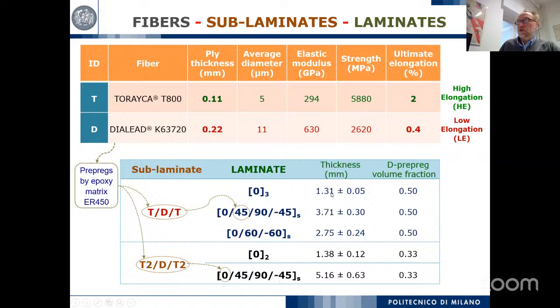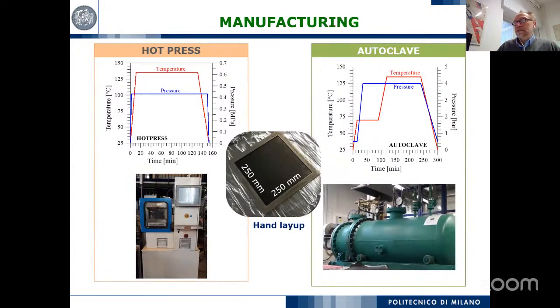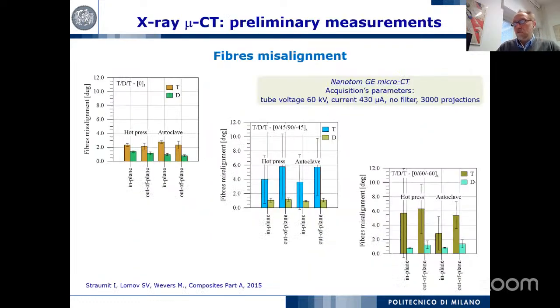And so you see here on this side the thickness that is more frequently used in the application, and the content of the low elongation fiber in the laminate. This is interesting to understand the final mechanical behavior of the laminates. Moving to the manufacturing, to understand if the manufacturing has an effect on the mechanical behavior, we used both hot press and autoclave with this manufacturing cycle after layup. And the first step was to assess the quality of the manufacturing, and this has been done with observation with micro CT to measure the fiber misalignment in the high elongation and low elongation plies.